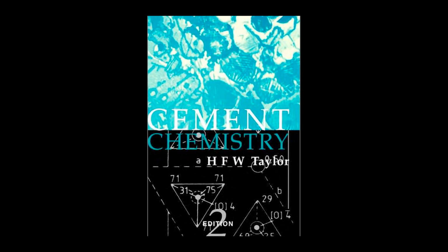Now, this reaction has a bizarre concentration dependency called the pessimum effect. Why does the worst damage happen at an intermediate concentration of reactive aggregate and not the highest? The pessimum effect is very counterintuitive, and it's a cornerstone of ASR research. If you have a low amount of reactive silica, the gel forms slowly and it's dispersed. If you have a massive amount of reactive silica, the reaction happens so quickly and consumes the available alkali so fast that the resulting gel is altered.